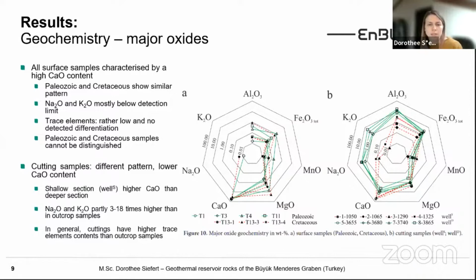And compared to the deeper section of the well, the shallow samples exhibit higher calcium content. And also here the concentrations of aluminium, iron oxide, and manganese are similar to the outcrop samples of the shallow wells, but the sodium and potassium concentrations reach higher values than in the outcrop samples. And the deep samples of the well show a major element pattern which is a bit different, and in general all cutting samples have higher trace element concentrations than the outcrop samples.